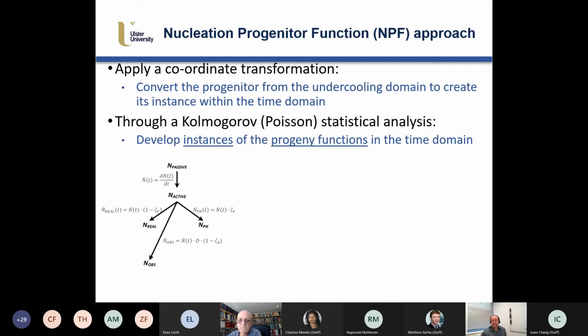So one of the things that we found, one of the benefits of looking at this NPF approach and looking at the Kolmogorov methods, is that there's a host of statistical tools available that give really good information if you look at it in this way. The first thing we do is apply a coordinate transformation. If you have the time-temperature curves, you can go from undercooling to a time-based coordinate transformation. That's very easy to do. You can do that through modeling, or I suppose you could do it experimentally as well if you had the cooling curves. But then we apply this approach, which is exactly the approach that I've just described to you. And we look at this here as the progenitor. And then down below, these children are the progeny of the progenitor.